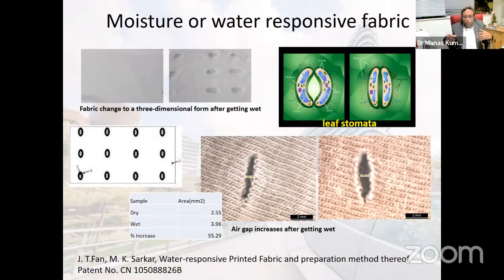Because when we sweat much, when our body is more heated, at that time, if it is possible to open up the pores and more moisture can be dissipated, definitely we would be much benefited out of it. So for this purpose, we used hydrogel. Different hydrogels are available, like PAM, like PVA hydrogel. So any kind of hydrogel can give such a property. So this is a regular knitted fabric with viscose fiber and with elastane, so that it's a highly elastic fiber. And we simply just printed this thing.